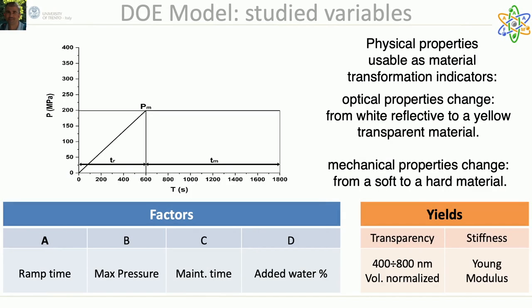The process was studied setting up a design of experiment using two observable physical properties as indicator of the material transformation: the change in the optical transparency measured as the optical transmittance in the 400-800 nanometer range, and the change in the mechanical properties measured as the increase of the Young compression modulus.